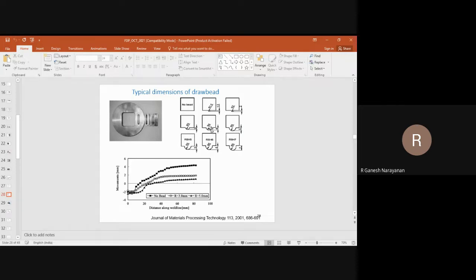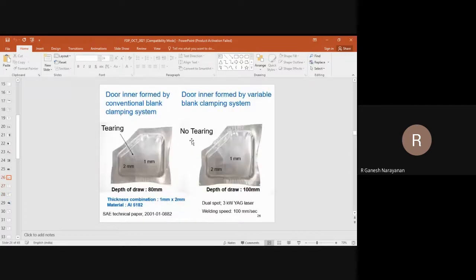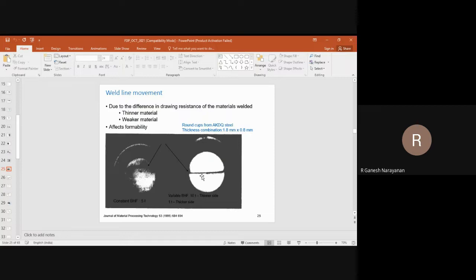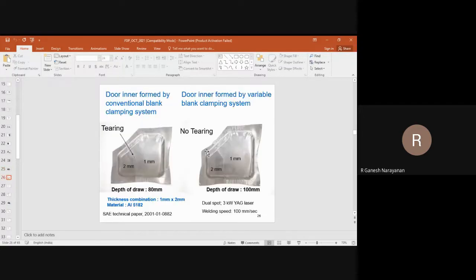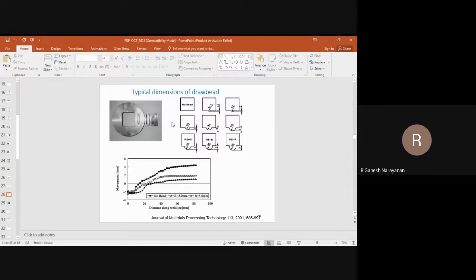Draw bead can be used on the thinner side. See, when you do deep drawing, one is thinner, one is thicker. No? The purpose of draw bead is to resist the sheet movement. Correct. So you provide draw bead or different profiles or dimensions of draw bead on the thinner side, while on the thicker side, you don't have draw bead at all. That way also you can resist the weld line movement. That's what is given here.